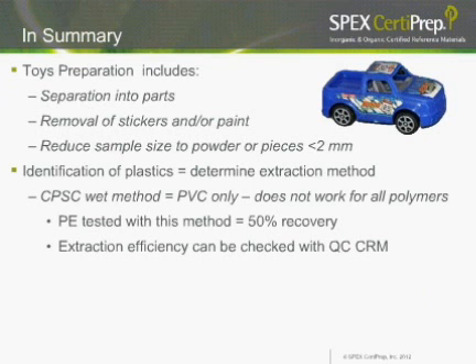We felt we needed to identify the plastics in order to best determine what extraction method we were going to use, which solvents we were going to use, what temperatures we were going to use in the microwave. If you use the Consumer Product Safety Commission wet method, it should really be used for PVC only. And according to the experiment we did with polyethylene, it didn't work as a good extraction method for our polyethylene material. Our polyethylene came at extraction of 50% recovery. You can always check your extraction efficiency by using a CRM or a QC sample.